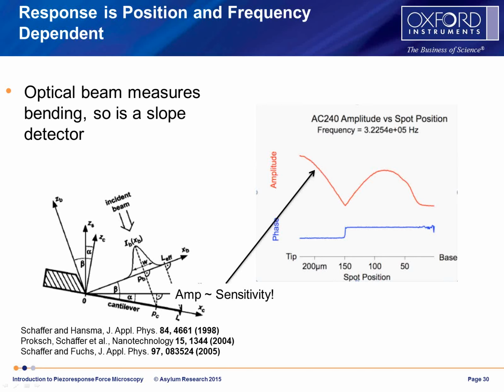That's a big deal, and it actually may go quite a ways as far as explaining the wide range of values we're getting with the histogram of the D33 in the PPLN sample, if you recall that histogram plot with all the different curves with a lot of scatter.